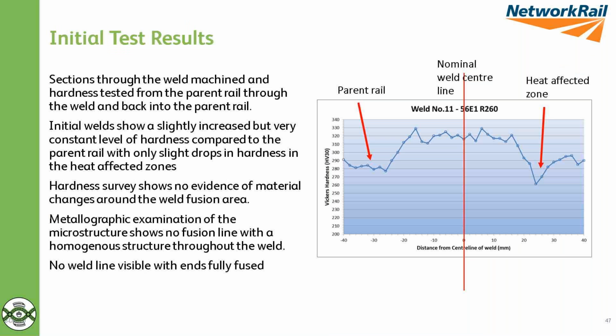It's quite a challenge to get it right, but this is a metallurgical section through it and a hardness test through the weld at the center there. You'd see very little change in hardness, perhaps a slightly improved hardness or increased hardness through the weld section itself up to about 20 millimeters away. A little bit of softening in the heat affected zone, but because the heating is quite rapid and very localized, we can minimize the effects of that overheating and softening. So from a continuous wear point of view, it's not something that should lead to localized cupping or wear of the weld. It's something where the hardness is maintained through it.